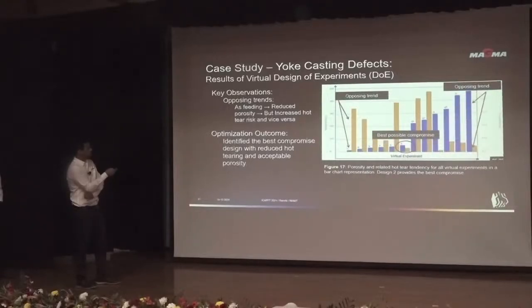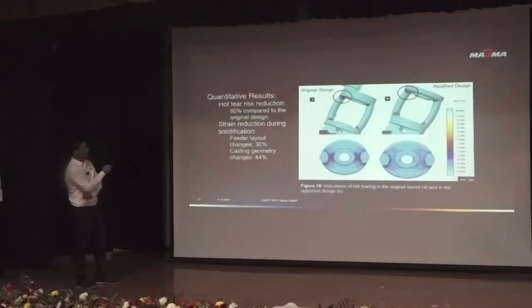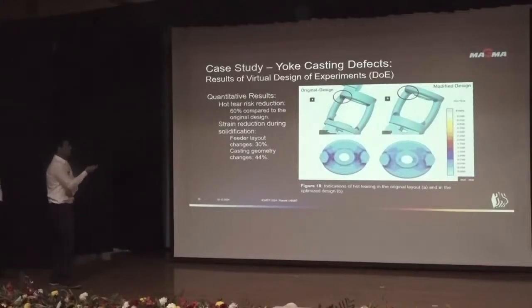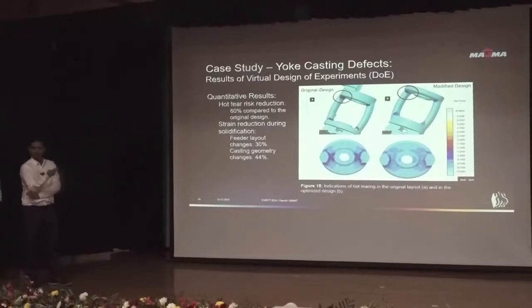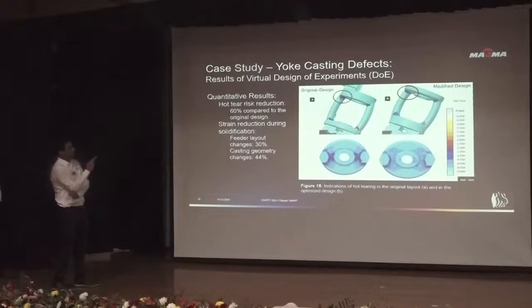So this is the best possible compromise. When we simulated that, we found that the hot tear risk was reduced by 60% compared to the previous design, the feeder layout was changed around 30%, and the casting geometry was changed around 44%. So this was the final result we got, and obviously there was no risk of hot tearing anymore.